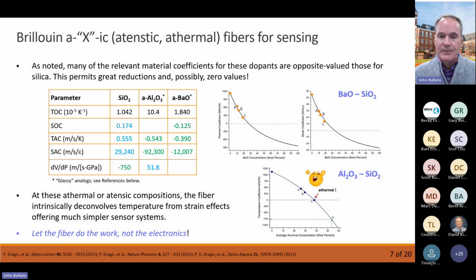And you see on the right, again, the temperature coefficient of Brillouin versus the strain coefficient of Brillouin. As you add, say, barium oxide into those silica fibers, you get significant reductions in that coupling, in that coefficient. And at certain compositions, they go to 0. We've not quite gotten there with the barium oxide dopant, but we have with the alumina dopant. So if you make an aluminosilicate fiber with high enough alumina concentration, which we have done, shown at the bottom there, you have a fiber whose Brillouin response is temperature independent.